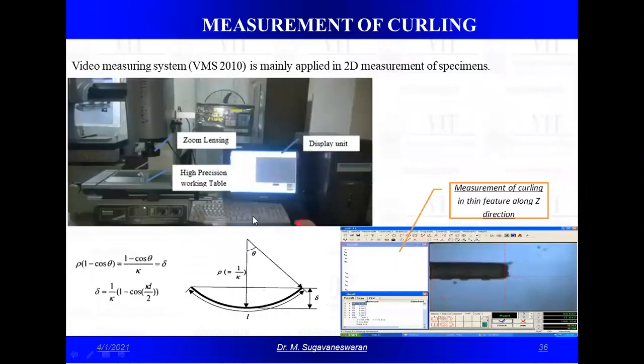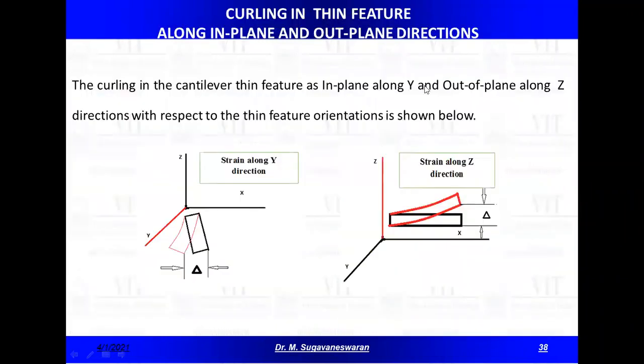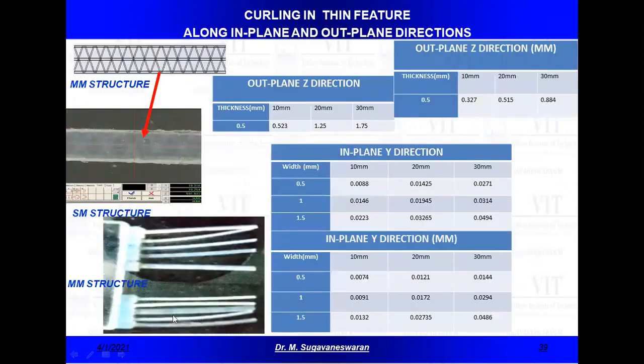So the results displayed here are for multi-material structure and single material structure in out of plane condition as well as in plane condition. Now we are further working on calculating, through analytical method, the individual elastic modulus of a layer, and accordingly varying the composition of primary material in secondary material across the thickness to control the distortion, that